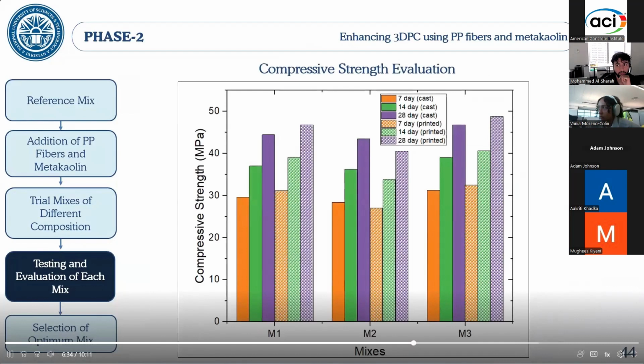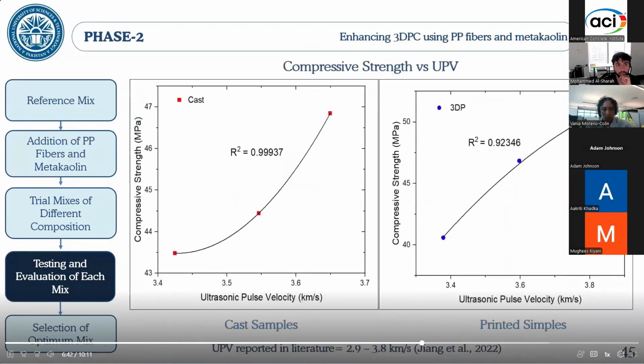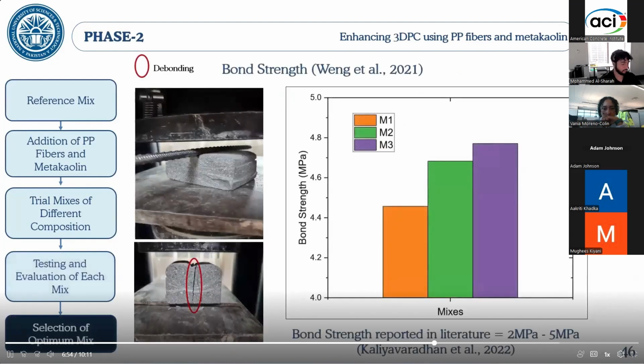This is an overview of our compressive strengths. Printed specimens showed higher strength due to the compaction caused by the nozzle of the printer. These are the plots between compressive strength and ultrasonic pulse velocity values of the specimens. This correlation can be used to predict strength of printed specimens as they exhibit higher strength variability. Lastly, we measured bond strength using this setup, and our strengths fell within the range reported in literature.